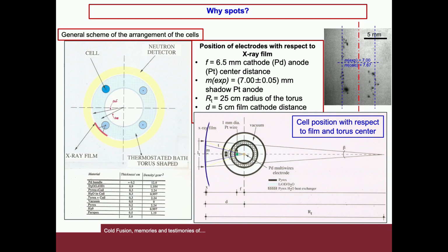If the cathode emitted radiation totally absorbed by the platinum, but completely transparent to the other surrounding materials, this would produce a shadow cone such as to obscure all the emissions generated in that solid corner. The distance between the two nearly parallel sets of spots measured on the film is 7 mm plus or minus 0.05 mm.